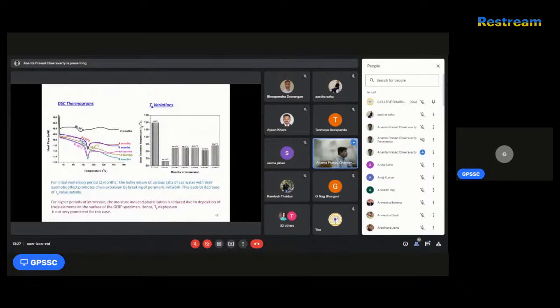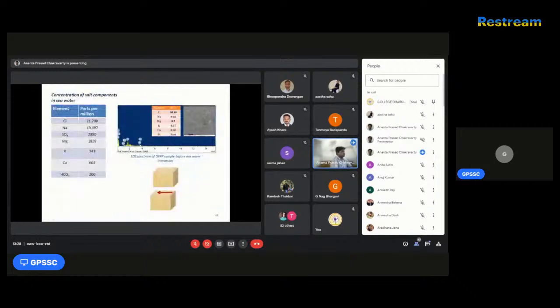Then, when we go to glass transition temperature measurement at onset values, we can see that from the zero-month glass transition temperature, it is no doubt decreasing initially, but gradually it increases up to a certain extent. So we have to understand in what way the salts are penetrating or deposited across the interface or into the material. First of all, we go for EDS analysis, where peaks at 0.4 to 0.7 are very small and insignificant. Then you can confirm that, without seawater immersion, those insignificant peaks are there, and they come from the material typically present in glass fiber. So we confirm that these are not due to seawater immersion.